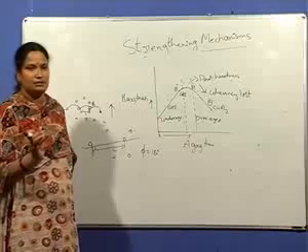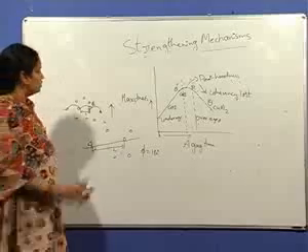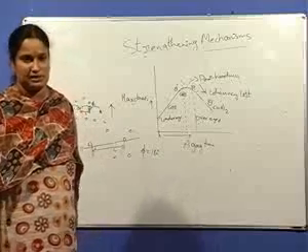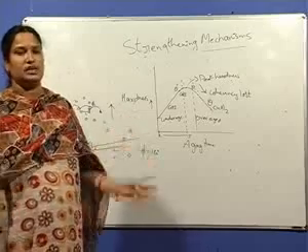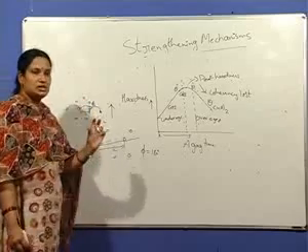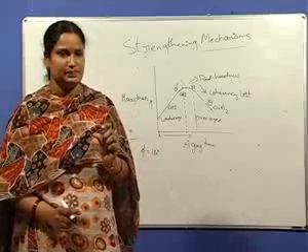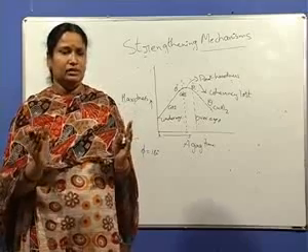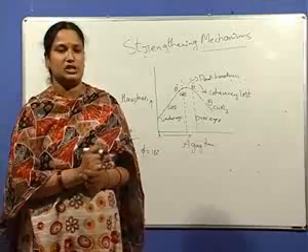The smaller the angle, the more stress is required for the dislocation to break away from the obstacles. The smaller the spacing, the more stress for the dislocation to break away from the obstacles. If the spacing is large, or if the angle is large, if it approaches 180 degrees, the dislocation almost need not bend. So the obstacles, that is the second phase particles, whether they are dispersoids or the precipitates, if they are fine and more in number, then they create more hindrance for the dislocation to pass.